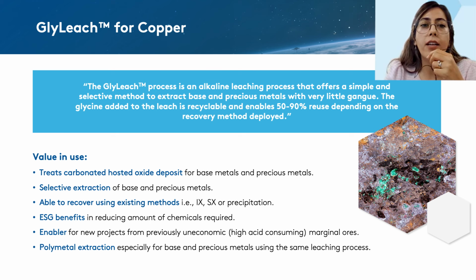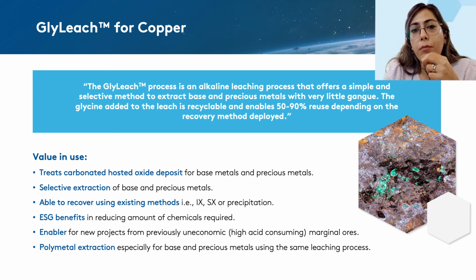So yeah, the glycine leaching technology, if applied in an alkaline system, can offer a simple and selective method to extract both base and precious metals, and there would be little iron left in the PLS solution, and the glycine added to the leach can be recyclable, and it can enable between 50 and 90% recovery depending on what recovery method we use.